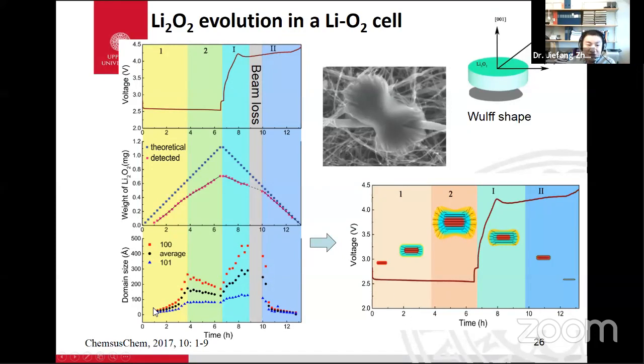At the beginning, you could see the sharp increase in the 100 direction. So we know it will get a 2D structure at the beginning, but then it will decrease, which means at stage 2, it will form small crystals at the edge of the disk. That's why you have the domain size decrease, because the domain size is the average for all the crystals. And the same for the decomposition. The first increase is because the small crystallites will decompose first, followed by a sharp decrease.